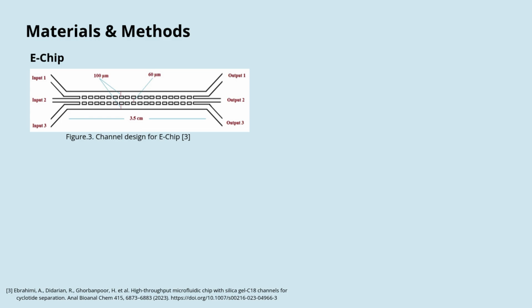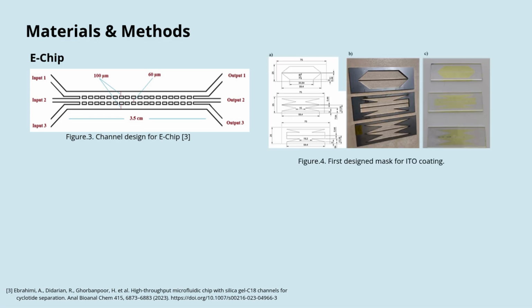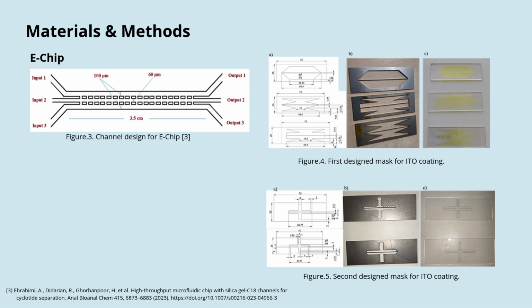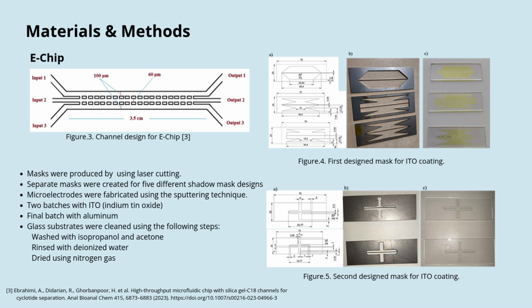The E-chip includes three microchannels fabricated in PDMS. These channels are bonded onto glass slides that are coated with conductive material. These glass slides are coated using different mask designs for layer deposition. Masks for the coatings were created via laser cutting.